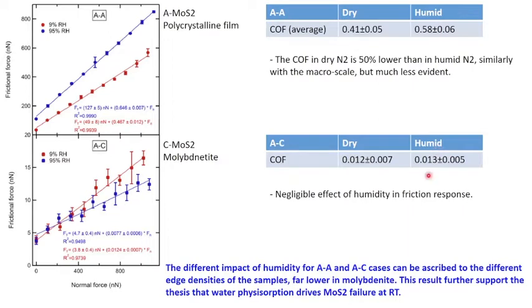This can be explained by the fact that if it is true that it's the water physisorption on the grain boundaries that is the origin of the failure of MoS2, we have to expect that in the case of a crystallographic structure, the density of the grain boundary is very limited with respect to the amorphous case. So in the case of a crystal, the number of water molecules that can physisorb and penetrate into the bulk is much less with respect to the amorphous case.